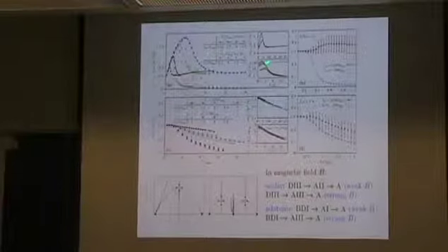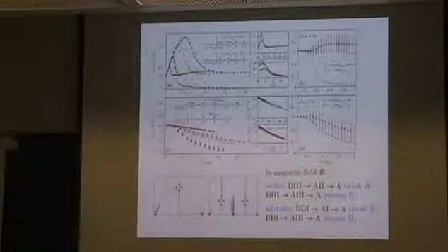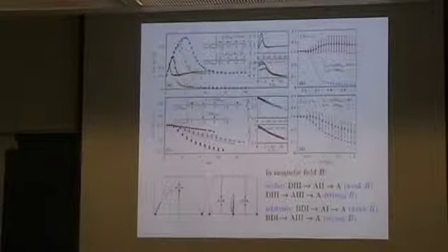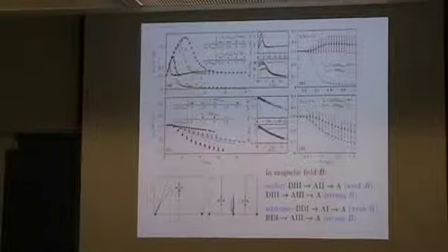Yeah, so here you see the flow into the quantum Hall critical point. Now, this happens also for finite strength impurities. At the moment the impurities are not symmetrically distributed, there is an average value of the potential, and it shifts the system away from the center of the Landau level, which means from the quantum Hall critical point. And therefore, we start to observe localization here. So even though valleys are not mixed, and before it was always critical, with magnetic field, the moment we shift from the center of the Landau level, from the quantum Hall critical point, we get localization.